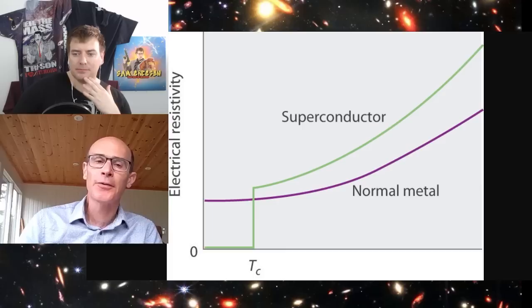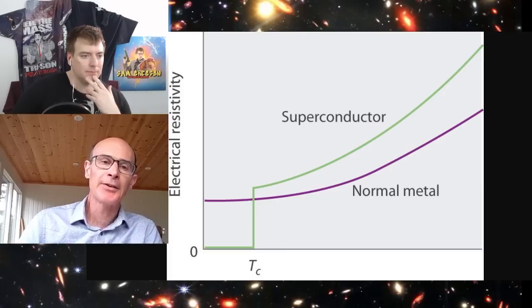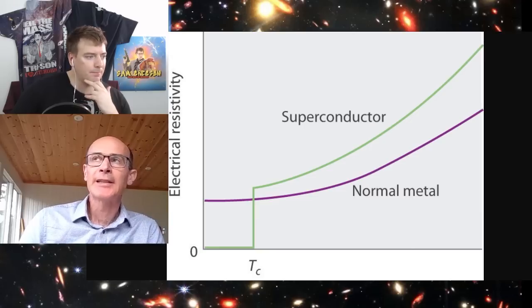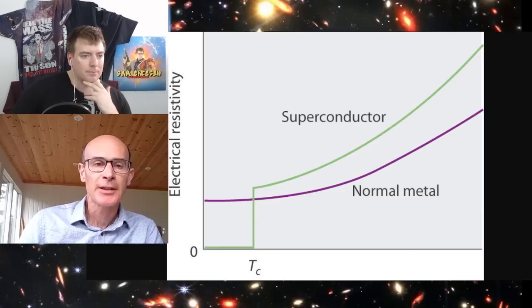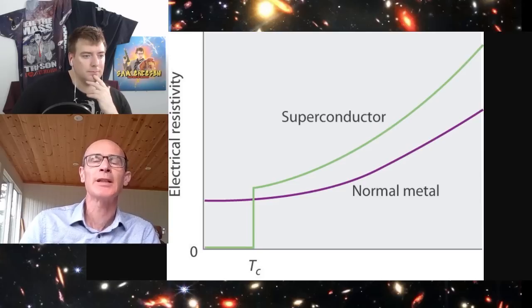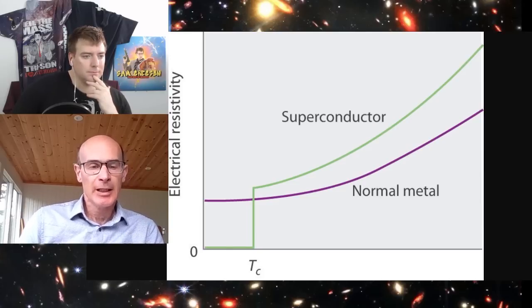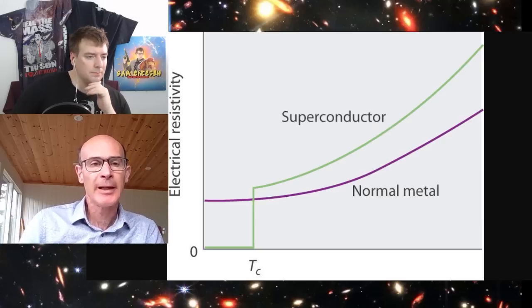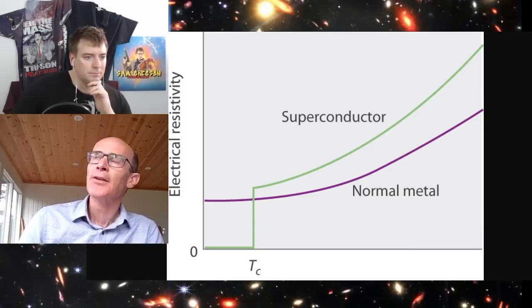You would turn on the field at low temperatures, and you would measure the magnetic susceptibility, how magnetic it is. You would get to the transition temperature, and the diamagnetism at that point will have gone away. And in most superconductors you would have a weakly paramagnetic sample with a temperature independent paramagnetism. That's characteristic of metals.